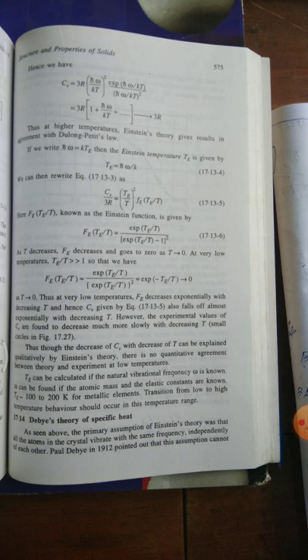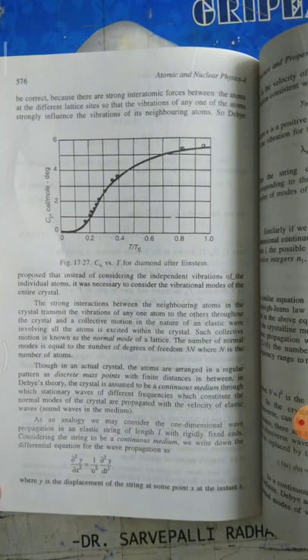It is Debye's theory of specific heat. As seen above, the primary assumption of Einstein's theory was that all the atoms in the crystal vibrate with the same frequency independently of each other. Paul Debye in 1912 pointed out that these assumptions cannot be correct, because there are strong interatomic forces between the atoms at the different lattice sites, so that the vibrations of any one of the atoms strongly influence the vibrations of its neighboring atoms.